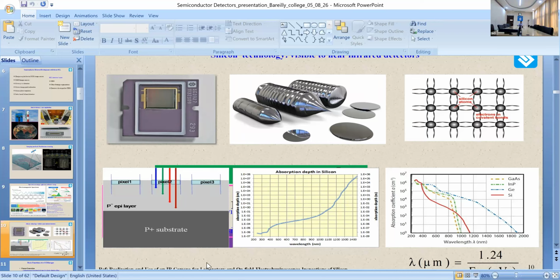Here the absorption depth is basically the depth at which around 70% of the incident light is absorbed. For silicon, to absorb light of 1100 nanometer, I need around 100 micron of thickness, and to absorb 70% of the light at a wavelength of 500 nanometer, I need a 1 micron thickness.